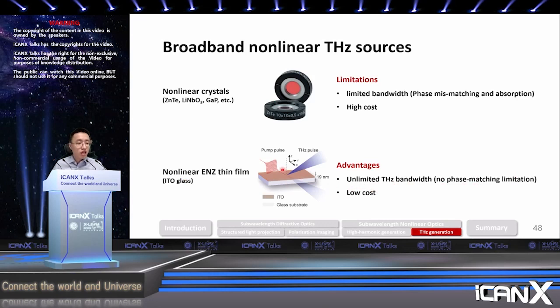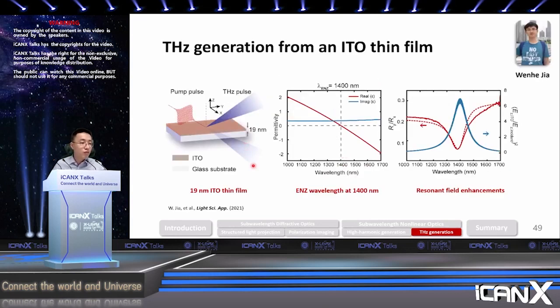In the experiment, what we are trying to do is use an IR laser beam to pump this ITO film. By using the surface difference frequency generation process, we are trying to see if we can generate any terahertz pulse either on the transmission or the reflection side. First, we bought a commercially available ITO film with a thickness of 19 nanometers, and we characterized its linear optical performance. I found that indeed it has a real part of permittivity crossing zero at about 1400 nanometers, with a corresponding large field enhancement.